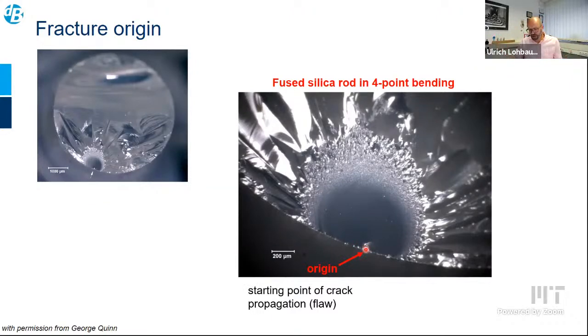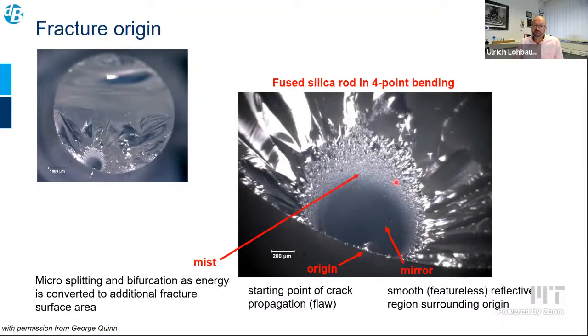This can easily be done with a light microscope. The origin of a fracture, the fracture mirror, this very flat and smooth surface. Then there is a mist region where the energy of the crack and the velocity of the crack is increasing. And then we have a coarse mist and the hackle region where the energy is increasing even more and the direction of the fracture planes are inclining, and those hackle and coarse regions develop by moving away from the origin.